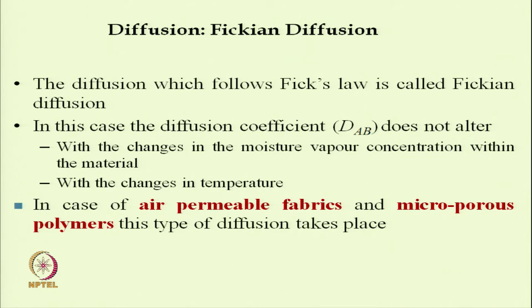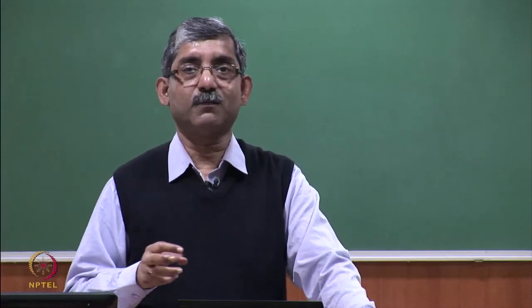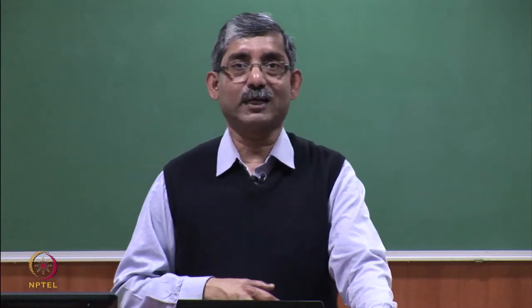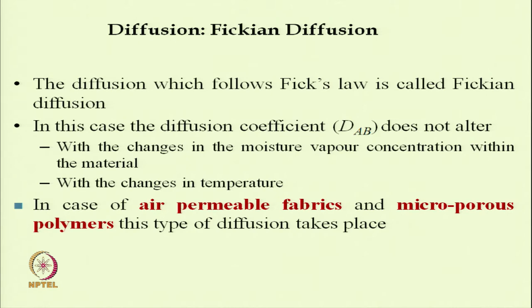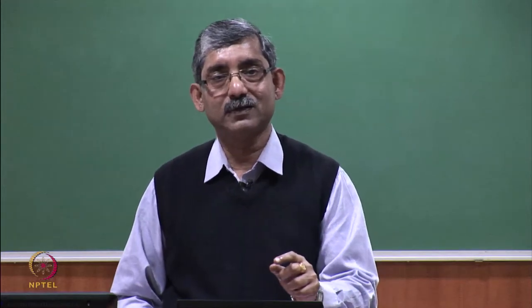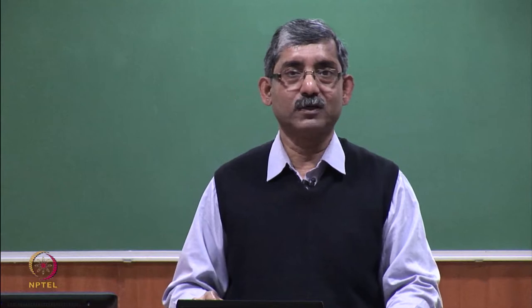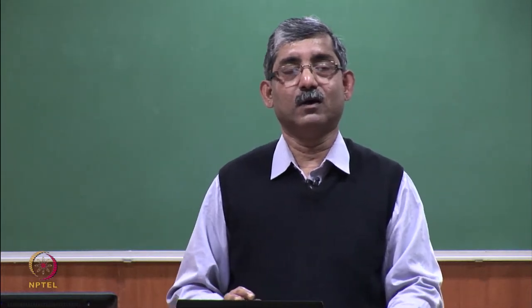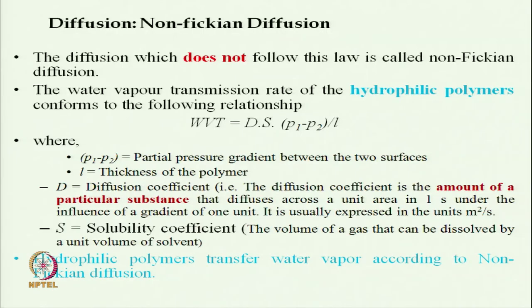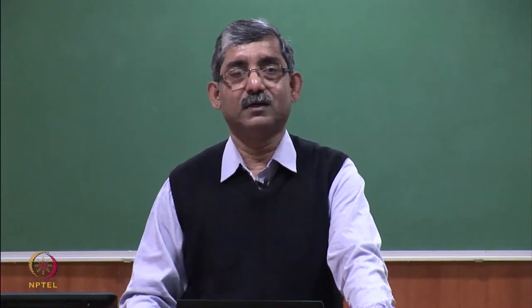So, if air permeability is there, that means the air pockets are present. So, Fickian diffusion takes place through this, where the polymer does not absorb the moisture, only between the fibers there will be air pockets and micropores, and through these micropores the water vapor gets transmitted. Another important diffusion phenomenon is the non-Fickian diffusion, where the diffusion does not actually follow the Fickian diffusion and mainly takes place in hydrophilic polymer like cotton, where the material absorbs the moisture.